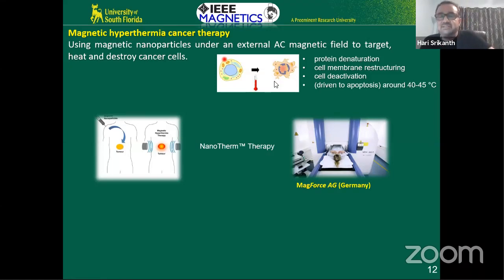And this happens, actually, you don't need to heat it up very much, just a few degrees Celsius above the human body temperature, okay? So the cancer therapy window is 40 to 45 degrees Celsius. So you need to be able to generate local heat of 40 to 45 degrees Celsius, and cancer cells die. They don't survive hot temperatures. They don't like Florida, for example. It was 36 degrees Celsius earlier today. So it's almost like Vellore here, the same. Okay, so we need to bring the cancer cells to Vellore temperature, summer temperatures, and that's how we kill them.